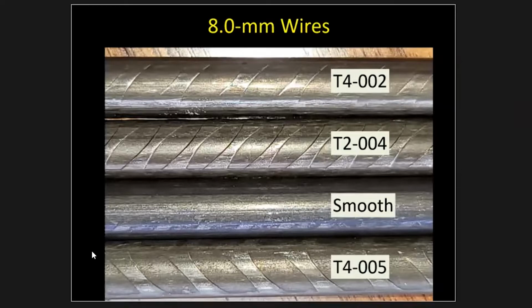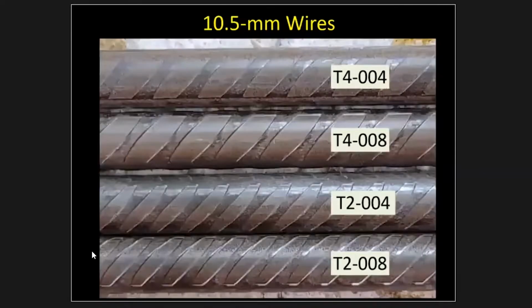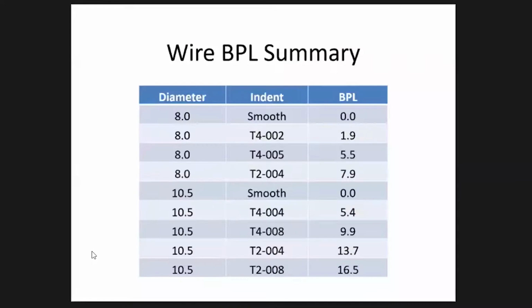The other thing with the T2, you notice this has a lot tighter pitch, and we did that to be able to explore various bite per lengths. So you can see the pitch of the T4s was a lot longer than the pitch of the T2. There are a lot more edges that are crushing and pushing concrete outward on a T2. For the 10.5mm wire, again, we had two T4s, two T2s. I didn't take a picture of a smooth. I figured you could picture that one. But you can see, again, the T2 style indent, in addition to being deep all the way around, is a lot closer pitch than the T4 style indent.